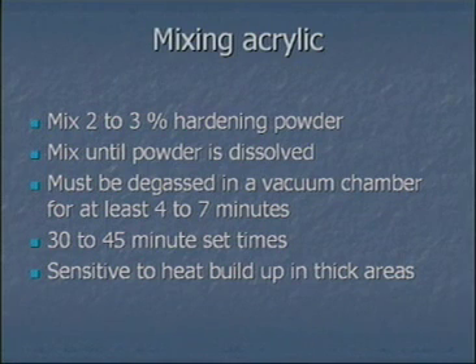They also tend to be very sensitive to heat buildup in thick areas. So if I have a model that I'm making and I'm pulling or laminating a socket over it, and I leave a lot of resin in one spot and it pools up and it becomes thick in that area, the heat is going to make the resin set off too quickly and it's going to bubble and crack in that area. So you have to make sure that you don't have too thick of a lamination anywhere. If you do, you could have some cracking and bubbling problems when it starts to cure.